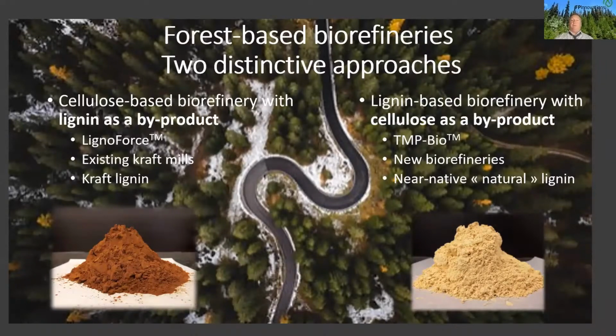At FP Innovations, we're pursuing two distinct and very complementary approaches to forest-based biorefining. The first, a cellulose-based biorefinery approach, whereas lignin is a byproduct produced from the isolation and evaluation of cellulose fibers in different applications. The second, a lignin-based biorefining approach, whereas cellulose derivatives, the sugars hydrolyzed from cellulose, are the byproducts, where the lignin that is produced is a near native, close to natural lignin with very distinct properties and distinct opportunities for applications.